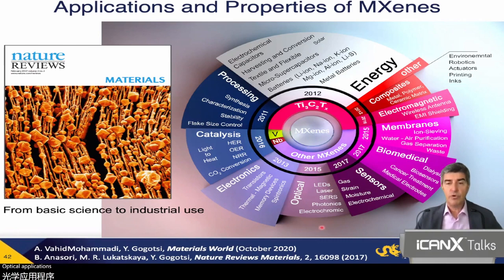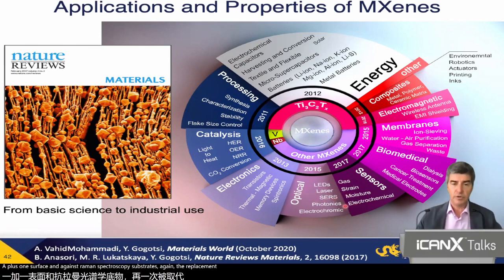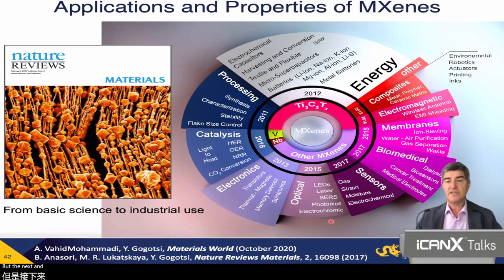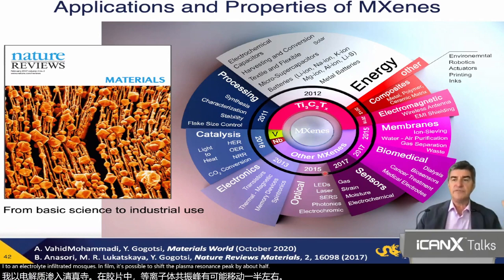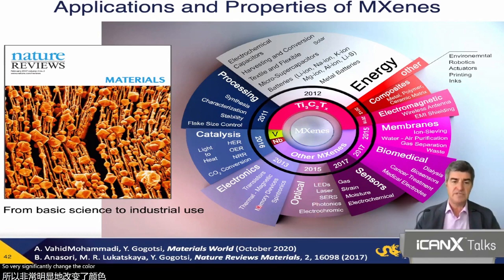Optical applications, recall all this variety of colors, so it simply means different optical and plasmonic properties, with application in transparent electrodes, lasers, actually femtosecond and random lasers, plasmonic surface enhanced Raman spectroscopy substrates, again replacing gold or silver noble metals, photonics and electrochromics. In MXene, by just applying 1 volt potential to an electrolyte infiltrated MXene film, it's possible to shift the plasmon resonance peak by about 150 nanometers. So very significantly change the color of these materials, similar to oxides, but because of conductivity, we don't require transparent oxide backing here. Many electronic applications that allow people to talk about MXetronics today.